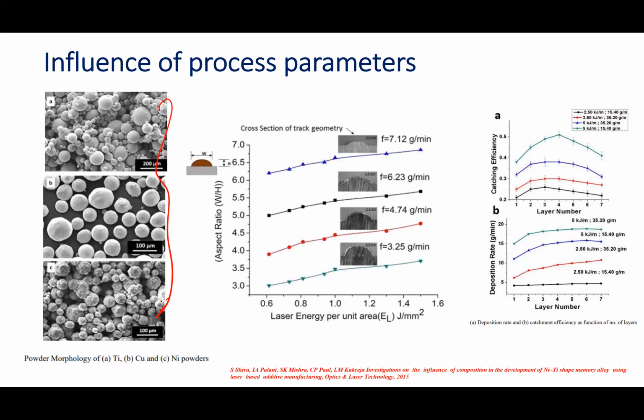The powder particles which were chosen were spherical in shape, which is pretty evident from the SEM micrograph, as spherical powder particles yield good density with no porosity in comparison to the irregular and flake shaped particles.